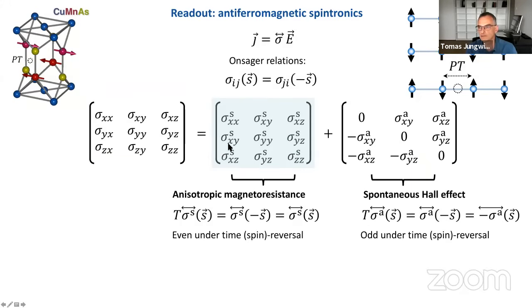When we talk about readout through resistivity in a simple film, let's take a look at this transport coefficient from a very general perspective. We can divide the conductivity tensor into the symmetric part and the anti-symmetric part with respect to the indices, where the indices correspond to the direction of the electrical current and the applied electric field. Now, if we combine this with Onsager relations, we see that the anti-symmetric component is going to be odd on time or spin reversal, while the symmetric component of the conductivity tensor is going to be even on time reversal. Now, when we look at this component odd on time reversal, the so-called Hall component, because it is odd on time reversal, it vanishes in systems which have time reversal symmetry.